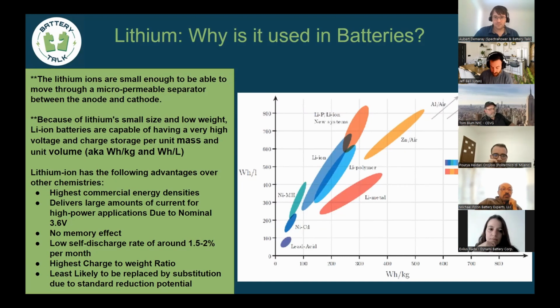Another thing is this memory effect. I don't know if you guys remember the nickel metal hydride and the nickel cadmium days, but older chemistry technologies tend to have what's called a memory effect. Essentially when you would do partial depths of discharge, another way to say you only use maybe 30% of the capacity window, the cell would actually start to remember that over time. And when you tried to go back to a full depth of discharge, that memory effect would negatively impact that, and you would artificially lose capacity of the cell, even though you were only doing partial discharges.